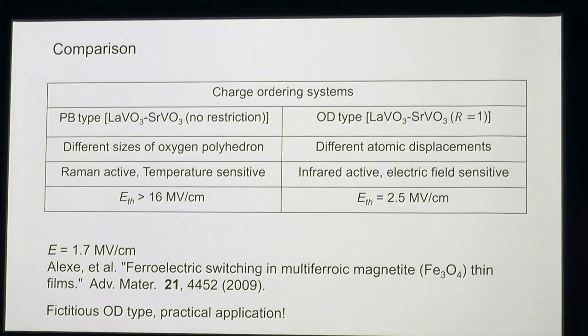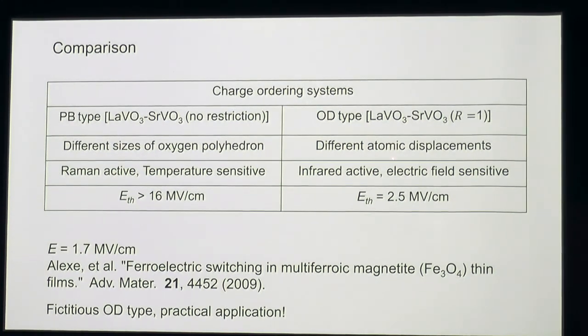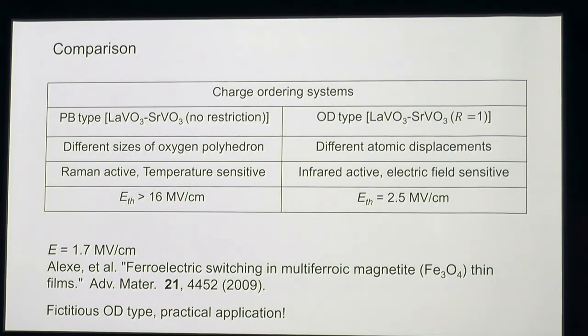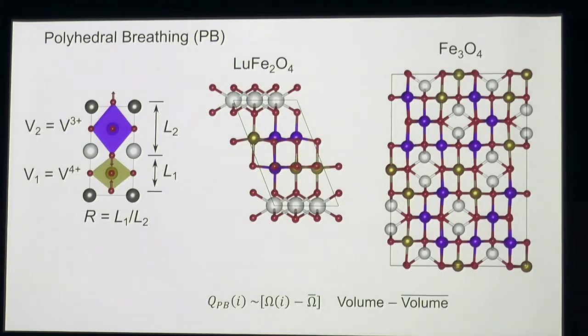Okay, so this page shows the comparison between the two types of charge ordering materials. The take-home message is that the polyhedral breathing type cannot have its polarization switched by an electric field because the lattice mode is infrared inactive. But the polarization in the off-center displacement type charge ordering materials can be switched by an electric field. But the example we use here is only a fictitious one. Later, we will apply our theory onto real materials, such as lutetium ferrite and magnetite.